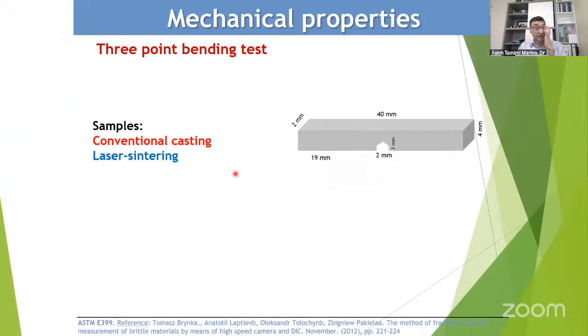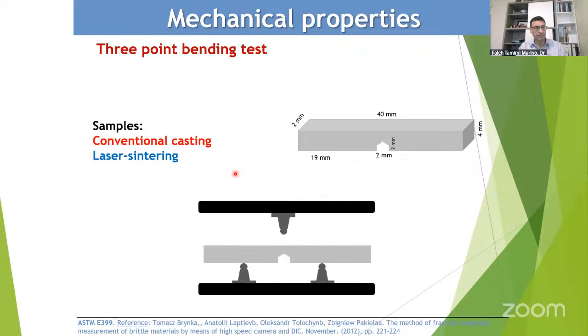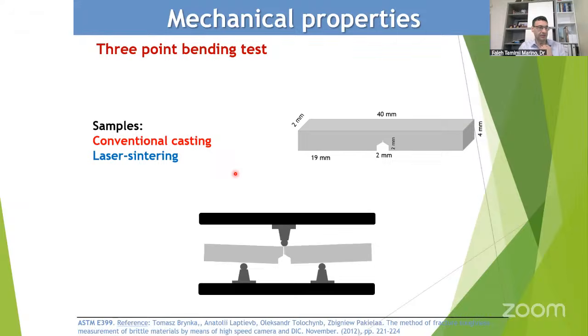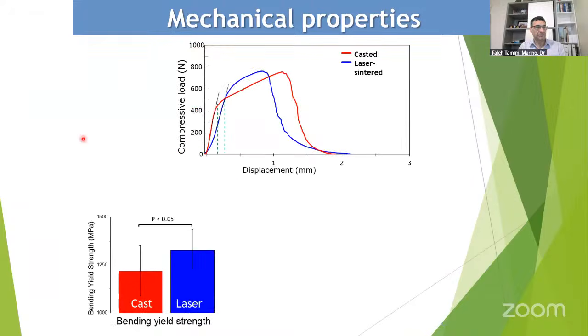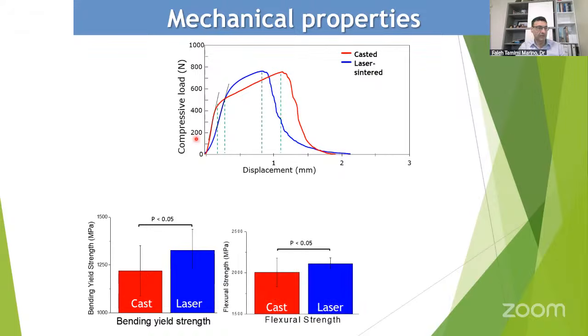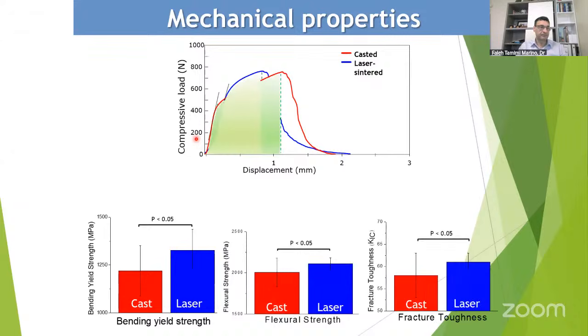We also tested the mechanical properties of these metals. So one of the issues with casting metals is that very often you get bubbles, and those bubbles in the structure could weaken the material. So we were expecting that this would be better than cast metal. Okay, so we did a 3-point bending test to test the strength of these metals and their fracture, and it turns out that indeed, they were stronger than cast metals. Okay, so they were significantly stronger and tougher also. So they were more difficult to break.